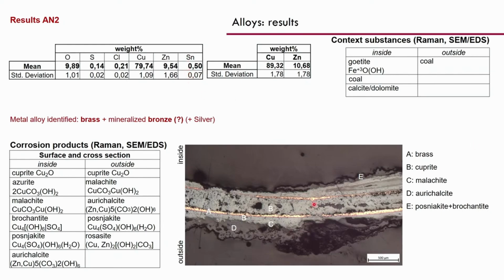So we can say, by the alteration process of this cross-section, that the bronze was present too, together with brass. Talking with Peter Holmes, he said that the tin could be a contaminant from the ground. So we can consider this hypothesis for this cross-section too. By the way, I just want to show you the mapping of the elements that we got. As you can see, we have copper and we have zinc here. And you can see that we have a fair amount of tin even in the internal side of the cross-section. And what is important to say, and of course as Claudia found, we have some low content of silver too.